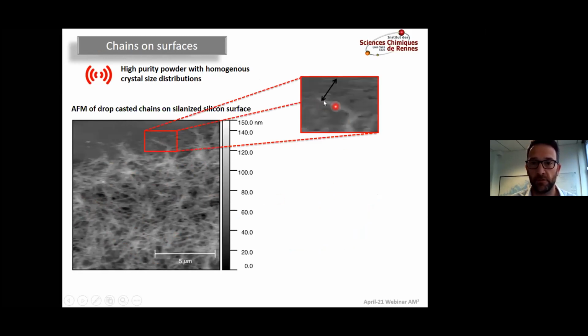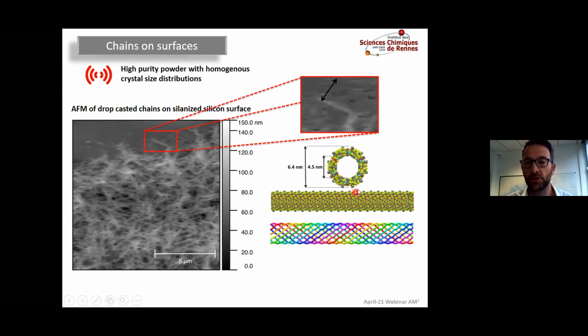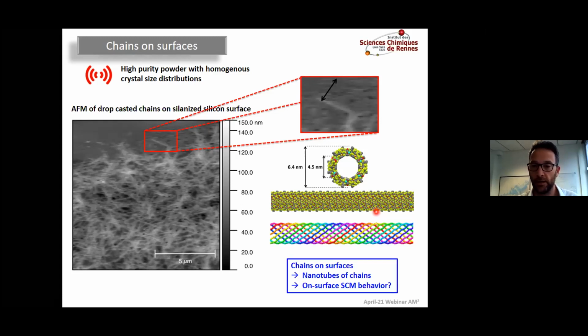And the dimension of the fiber, oh, my arrow moved a little bit, is totally comparable to the dimension of a nanotube. So we are quite confident that we have nanotubes on surfaces, and this shows that this organization of chains into a much more robust supramolecular architecture is a nice way to put these chains on surfaces. And we are now looking for beam times to be able to measure the on-surface single chain magnet behavior. We have new developments on this, but unfortunately we are in a patenting process, so I can't say more.